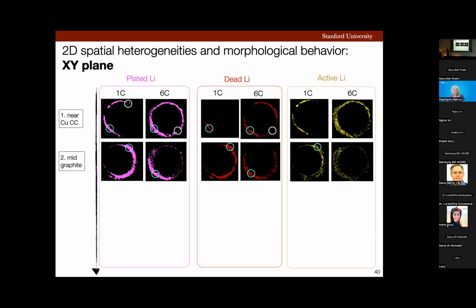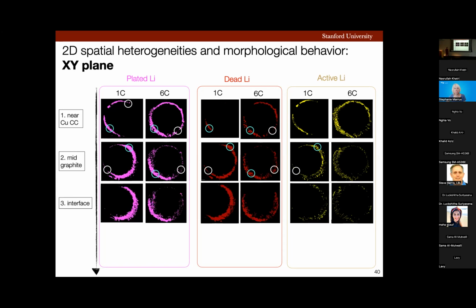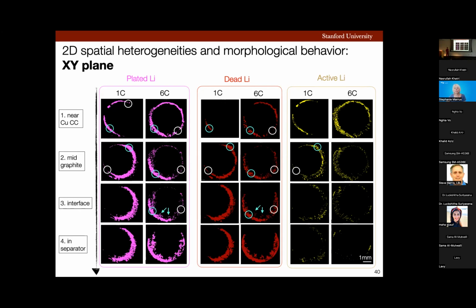Sorry about that. Now, if you look at the second region, which is mid-graphite, you would notice that at 1C, we are looking at a higher amount of plated lithium as compared to near the current collector. We also see that regions that formed the most plated lithium at both 1 and 6C are the ones that formed more dead lithium. Same is true for regions that formed less plated lithium; they are the ones that formed less dead lithium. Now, if we look at this interface, we notice these crescent moon-like geometries that are present at 1C and also at 6C. Spatial heterogeneities are again observed at this region as well. But in addition, we also started seeing these tip-growing growths that are appearing at the interface at 6C. Now, in the separator, these tip-growing growths are more evident at 6C.